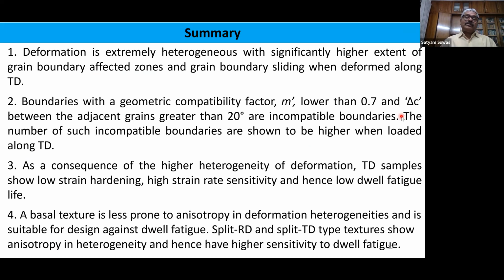The boundaries with a geometrical compatibility factor m prime lower than 0.7, and delta C, that is the angle between the adjacent grains, greater than 20 degrees, are incompatible boundaries. The number of such boundaries is higher when loaded along TD. Therefore, it is more prone to the dwell fatigue situation. And since there is a higher heterogeneity of deformation, the TD samples show low strain hardening, high strain rate sensitivity, hence low dwell fatigue life. That means they are more prone to dwell fatigue. They are not good as far as the application point of view is concerned. And this also shows that basal texture is less prone to anisotropy and deformation heterogeneities and is suitable for design against dwell fatigue.